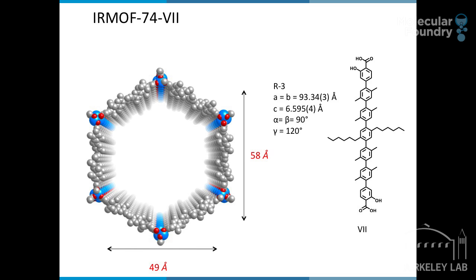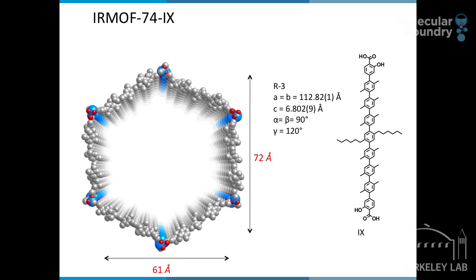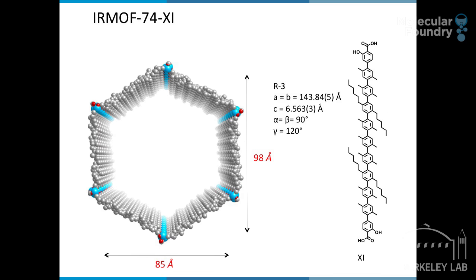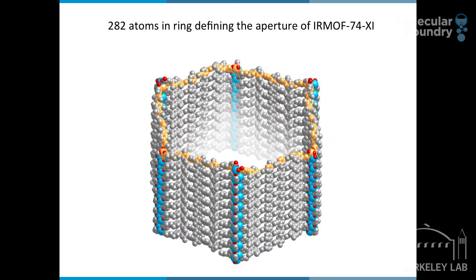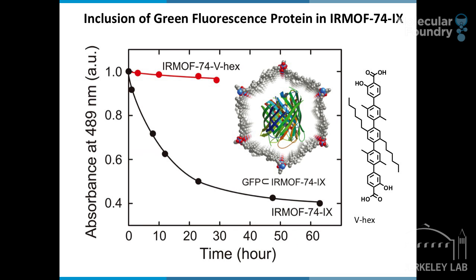8 is missing for various reasons dealing with the synthesis of the link, but 9, and up to 11, 98 angstroms by 85 angstroms. That is the largest pore opening of any porous crystal known. Very exciting because a material made from such a long link really gives us a lot of ideas on where this chemistry can go. One idea is that the pore opening now, 282 atoms wide, can fit a protein as large as GFP, green fluorescent protein, without the protein being unfolded in the pore. In fact, in this particular example, the MOF with 6 phenylene units can fit such a large unit.